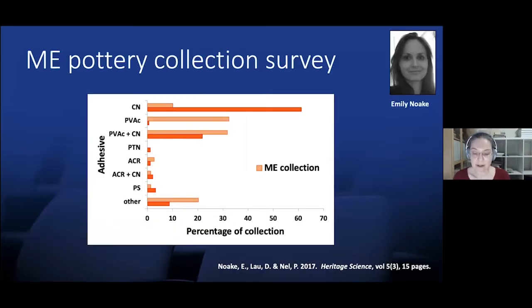A later survey of the Middle Eastern pottery collection by a PhD student, Emily Noak, further interrogated adhesive formulations to which cellulose nitrate had been added, with a third of repairs being found to be due to polyvinyl acetate, where cellulose nitrate was added to the formulation, most likely to the commercial product UHU All-Purpose.